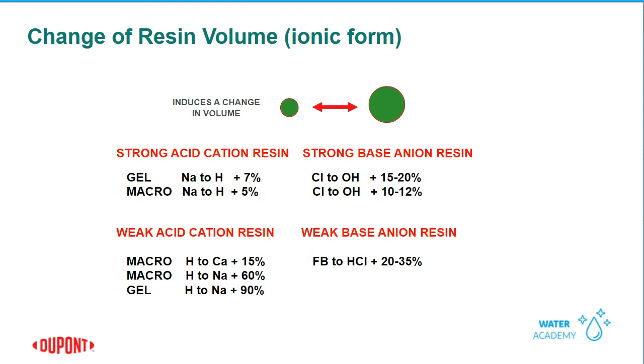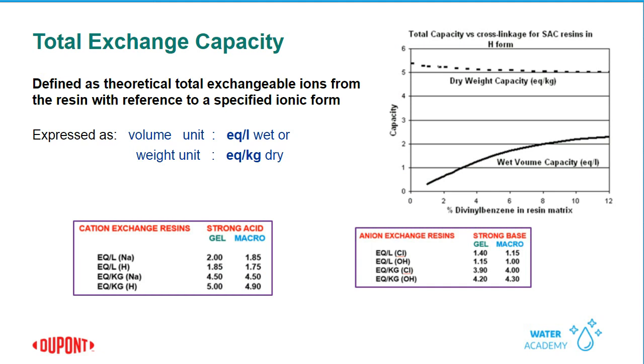The total exchange capacity is the number of active sites that are available on the resin with reference to a specific ionic form. This is usually expressed as a volume unit. So you may see equivalents per liter, and in parentheses, the form like sodium or hydrogen if this is a cation resin. Another way of expressing this is by weight, and this unit is not so common, but you may see it here and there as equivalents per kilogram, and that is a dry measurement. So on the bottom of the screen, in those two blocks, you can see typical examples of cation exchange resin capacities, as well as on the right, the anion exchange capacities.